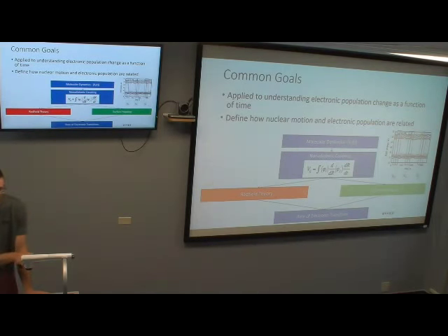But once you start adding things, even in perovskites, when you have organic ligands, materials that fluctuate and move or rotate quite a bit, it plays a larger role in how the electronic energies shift because now you have drastic orientation changes. So surface hopping can be very useful in those situations.